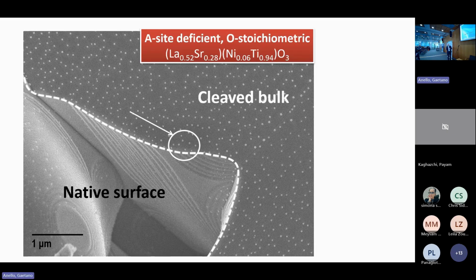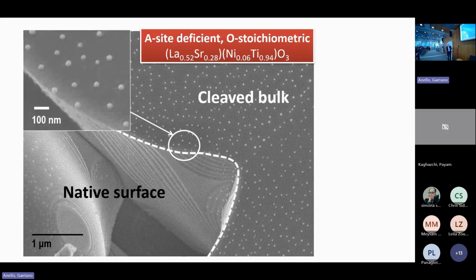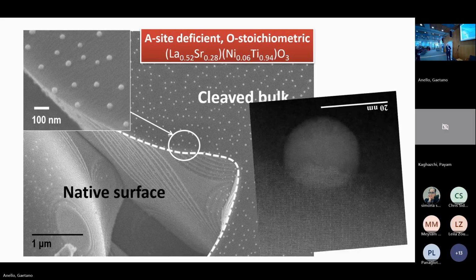So 6% nickel, 20% deficiency on the A-site. And you can see that even up to the cleaved surface is pure perovskite, whereas the native surface is a little bit strontium rich. So as you expect in perovskites, you get the exsolution on one surface, not the other. And the particles are not on the surface, they're sitting in the surface. So they're actually in a pit. And if you dissolve them with acid, you find pits behind.